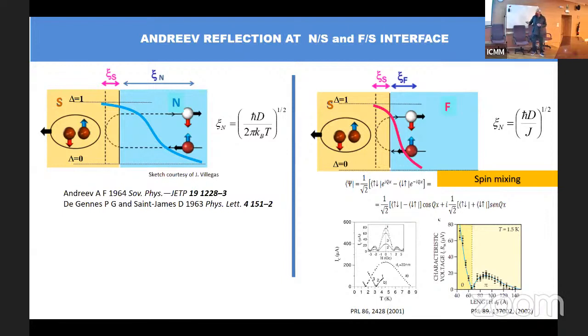But looking at the Andreev pairs in the ferromagnet, one is spin up, the other is spin down, so they have to pertain to different bands, right? As a result, there is a center of mass momentum in the pair. So the wave function of the pair is like this, right? Which can be shown very easily to be decomposed into a singlet component and a triplet component. And this triplet is not the triplet we're looking for. This is a triplet with zero Z-spin momentum, right?